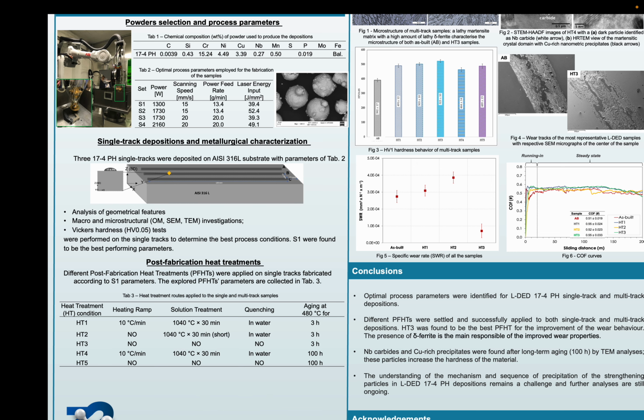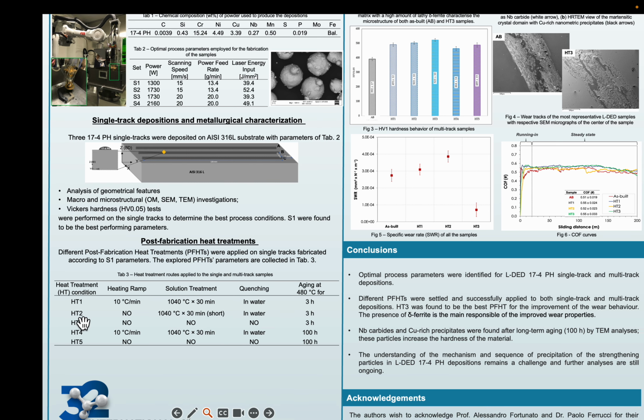In addition to this, three different post-fabrication heat treatment routes based on the H900 treatment specification for this kind of materials were applied, as we can observe in the figure. The first corresponds to the H900 heat treatment, and the second and the third correspond to variations of the first treatment: HT2 with no solution in the case of HT3, and with a short solution treatment time. In the third case, the heat treatment was directly aged and no solution was applied. Besides that, two other long-term aging treatments, which were based on the HT1 and HT3 respectively, were applied to the samples. In this case, 100 hours of aging were applied with and without the solution treatment step.